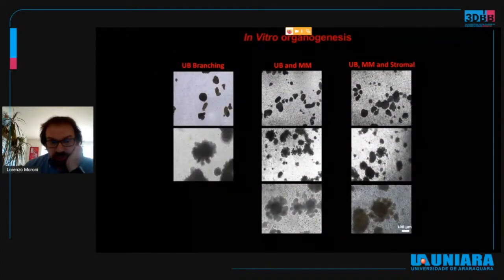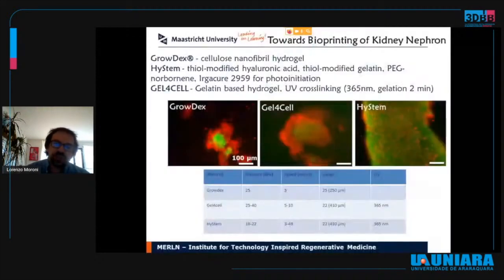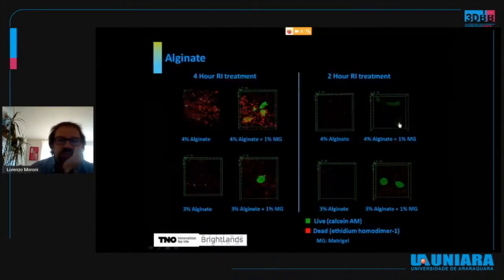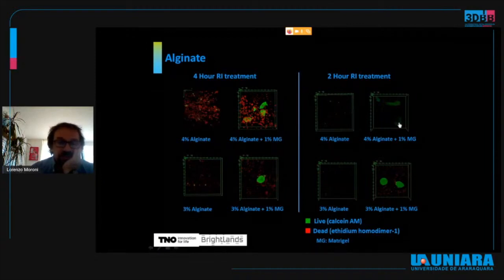We then also went further down into either ureteric bud or metanephric mesenchyme progenitor cells. And you can see here the typical feature of these ureteric bud cells is the formation of branching structures. We then started to look at bioprinting, but here we started to face the challenge of how delicate iPS-derived cultures are to be deposited, where in principle, considering different commercially available gels, only HyStem, which is a modification of hyaluronic acid with PEG and gelatin, resulted in some level of acceptable viability, despite the fact that here you still see a high number of cell death, which is something we still have to improve upon.